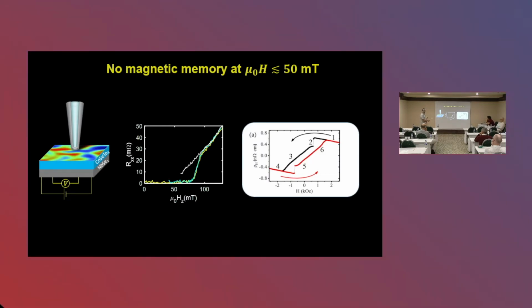So I bring you back to the initial data that I've shown, where I told you these guys measured a finite anomalous Hall. Why is that the case? We thought about many different interpretations. Maybe it's the effect of the platinum that hybridizes and stabilizes the magnetization. But maybe there is a tiny part of the sample that does stay magnetized, and we're missing it, even with this transport measurement and even with our imaging.